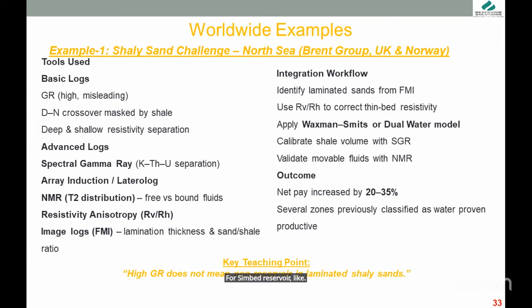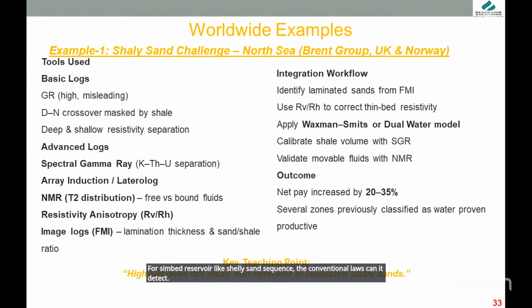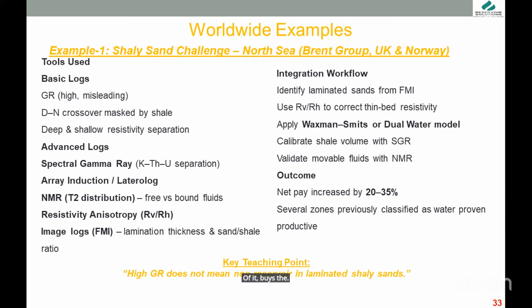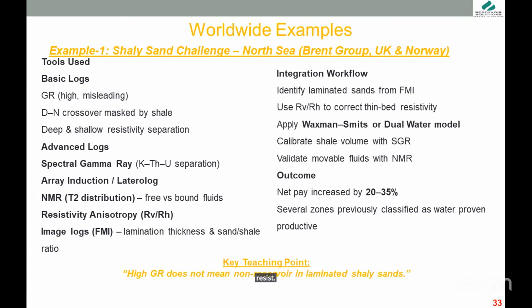Array induction laterolog and RVRH, because for a reservoir like a shaley sand sequence, the conventional logs cannot detect the ideal thickness because it ranges between 1 to 2 feet. If you have one streak of 0.5, 0.6 feet, you cannot detect it by the conventional logs. So the resistivity will average all the zone, and the maximum of it by the shale, so the resistivity will decrease dramatically. For this reason, we used RVRH, vertical resistivity and horizontal resistivity. It's better for your identification.